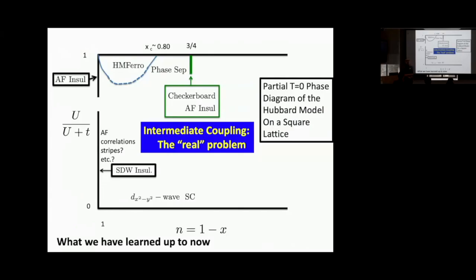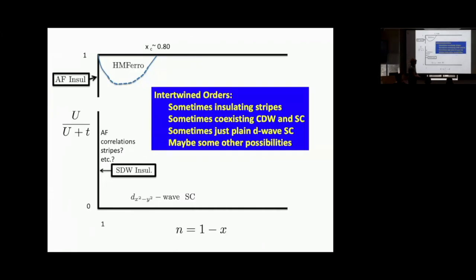Okay, good. So what have we learned up till now? So what I think we've found is that in the Hubbard model, what's really clear is that we do have this phenomenon of intertwined orders. There are many ordered states that are in some extremely delicate dance with each other. And somehow we have fine-tuned something. We've tuned U to be on the order of the bandwidth. So there's some degree of optimal quantum frustration. The system doesn't know whether it wants to order in real space or in momentum space, but it's not highly tuned, and it's only one thing, and that produces this remarkable panoply of different ordered states.